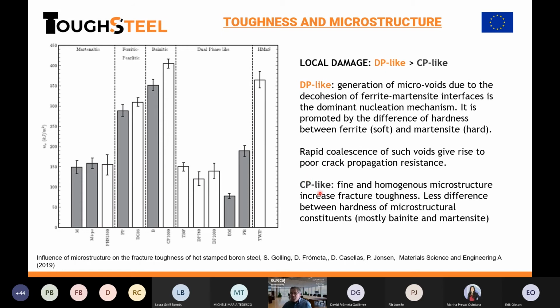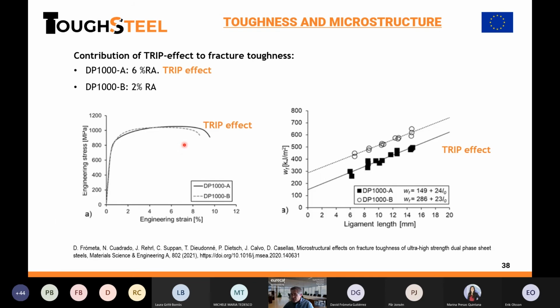On the contrary, in CP-like microstructures like this, we see that the toughness is high. Toughness is high because it is homogeneous and can dissipate energy during propagation. If you look at other microstructures that do not have higher toughness but are homogeneous, like martensitic microstructures, we see that toughness is more or less similar. It is not a big variation, because again, the more homogeneous the microstructure is, the more homogeneous the toughness is. So fracture toughness can also be used to understand the effect of microstructure on the properties.